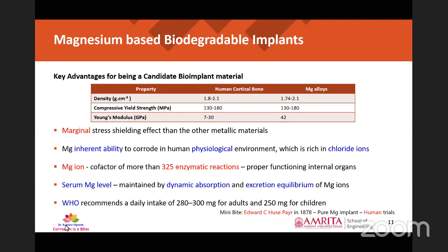The first is the density, compressive yield strength, and Young's modulus. And why? Because the density of human cortical bone and the magnesium alloys are very similar, and the compressive yield strength and Young's modulus are going to be very similar to that of the magnesium alloys in most cases. Added to that, this equivalent compressive yield strength, Young's modulus, and density will give us only marginal stress shielding effect if it is implanted in the human body.